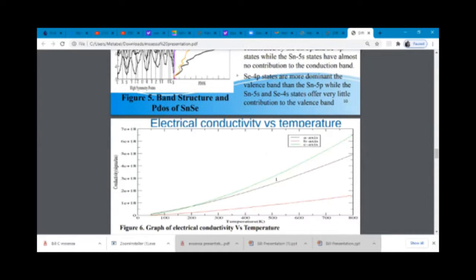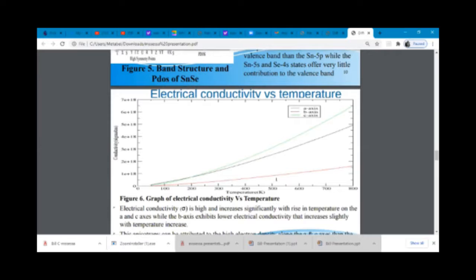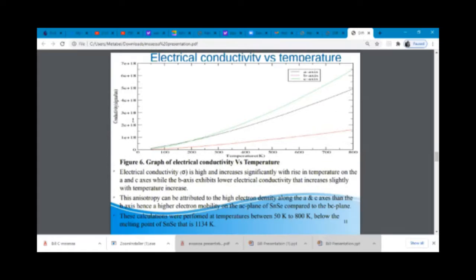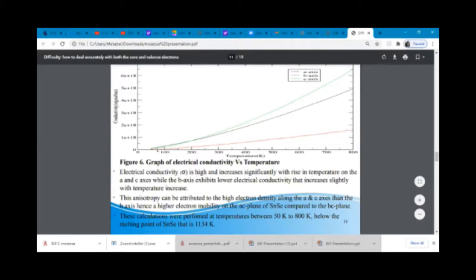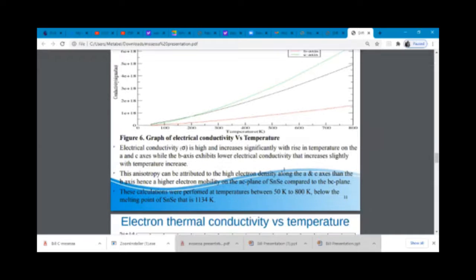And then this is the variation of the electrical conductivity versus temperature. The graph in figure 6, the y-axis, the conductivity given in sigma per tau, that is sigma in terms of the relaxation time, and the temperature increased from 50 all the way to 800 Kelvin. So the electrical conductivity was found to be directly proportional to temperature, which suggests a semiconducting property.